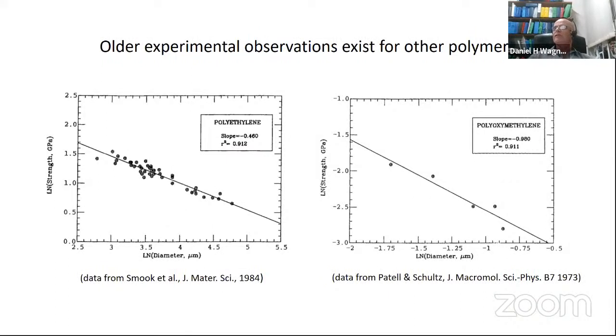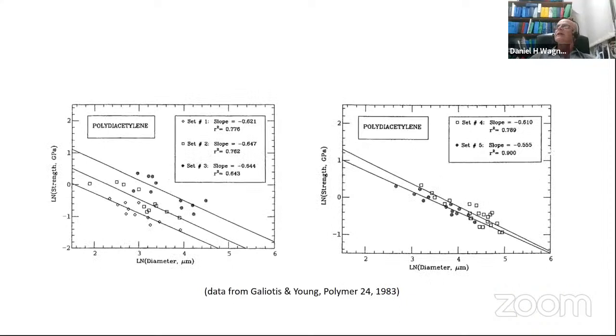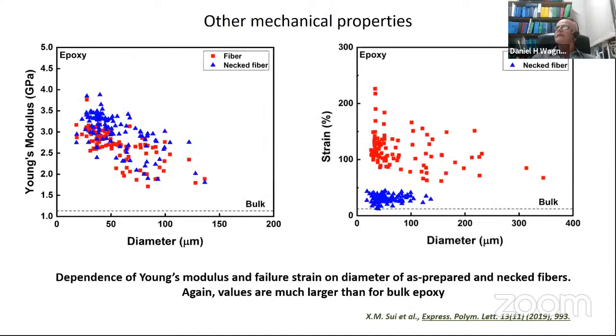Is there anything else in the literature regarding this? Well, if you dig deep enough, you find things for polymers. You see 1984, there is polyethylene. The strength is plotted as a function of diameter. And for polyoxymethylene, you also have very few data points, but there is also a slope of 1/2 for polyethylene and -1/2, and 0.9, minus 0.9, for polyoxymethylene, that's not very good in terms of the models. And then we have polydiacetylene of various brands, again in the 1980s. So things exist.